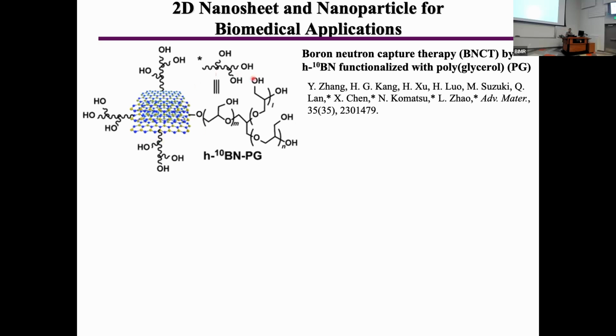Then we functionalize the surface of this nanoparticle with polyglycerol. PG stands for polyglycerol. You may know PEG, polyethylene glycol. It's a very typical hydrophilic polymer. If you inject the vaccine for COVID, it's also functionalized. So the surface was functionalized with PEG, polyethylene glycol. But we know that this kind of hard inorganic nanoparticle cannot be fully dispersed by polyethylene glycol. Hydrophilicity is not enough, unfortunately.